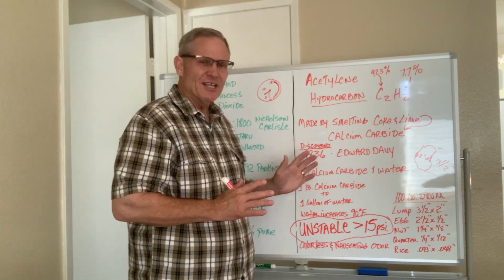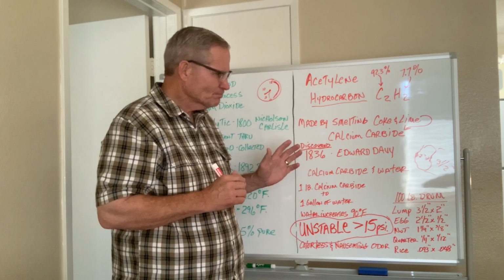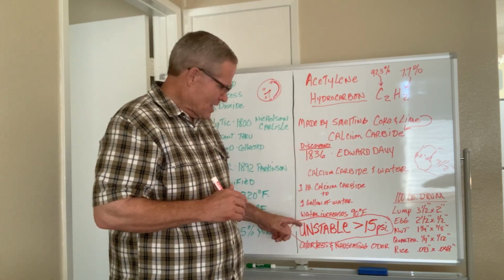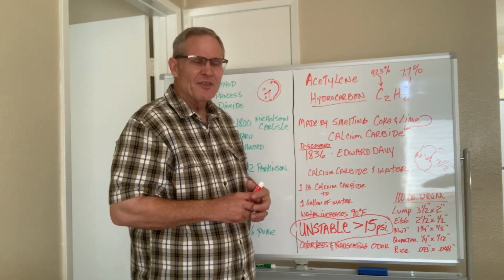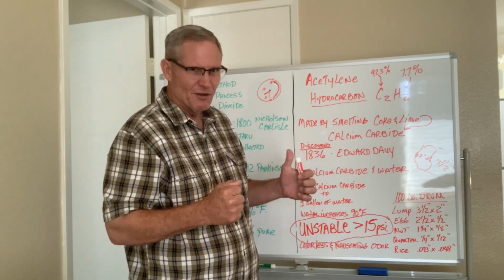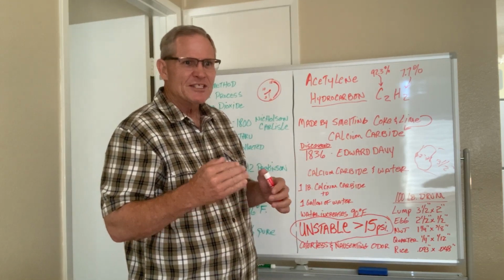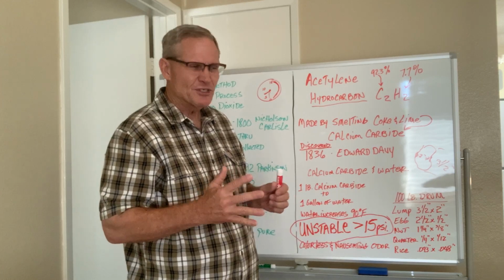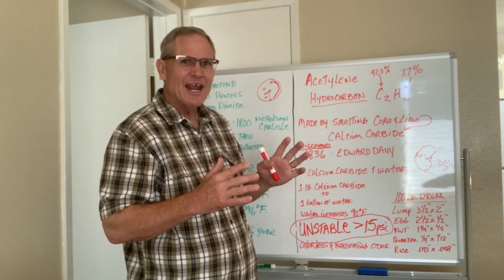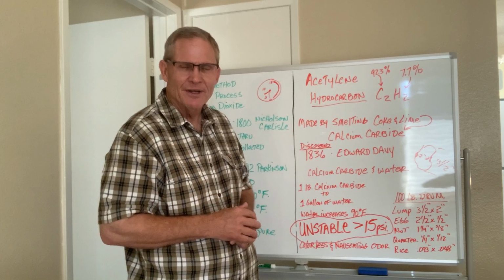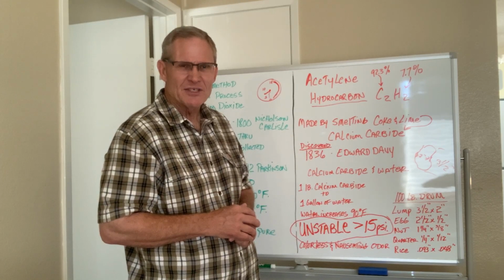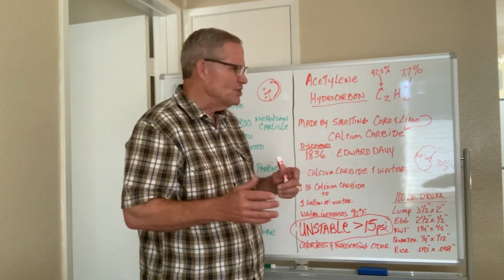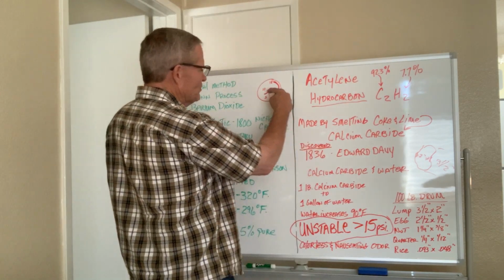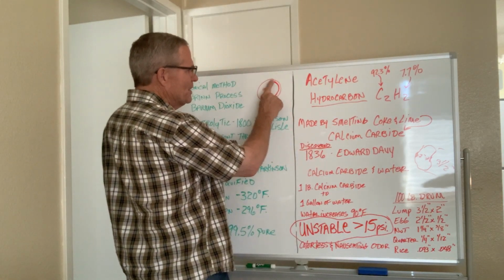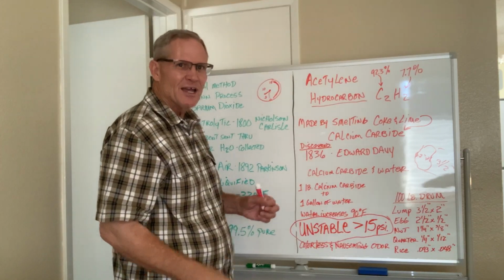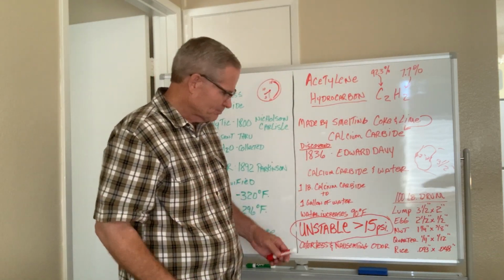What happens is that the gas itself becomes unstable above 15 pounds. The hydrogen tries to separate itself from the carbon. Temperatures increase and pressures increase. You can have a spontaneous combustion above 15 psi. So what I'm suggesting to you is that at no time should the needle on the regulator be above 15 psi while you're using it.